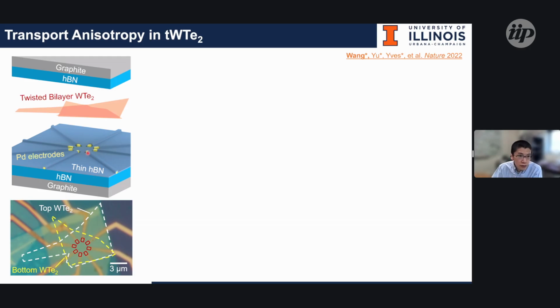We developed a point contact method where we have the electrode exposed at the edge or tip of the electrodes, which lets us really contact the sample in the bulk of the twisted tungsten ditelluride. Another reason for using this method is because monolayer tungsten ditelluride has a topological edge mode.